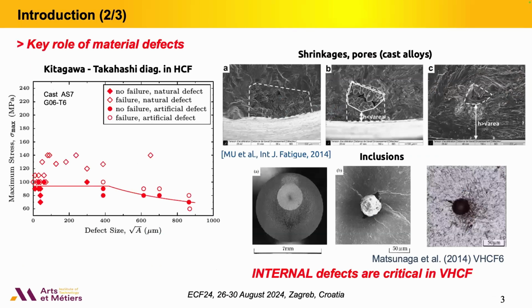So in very high cycle fatigue, the role of defects as a crack initiator, or trigger for the crack initiation, is very well known. In a high cycle fatigue regime, around 1 million or 10 million loading cycles, there is the very famous Kitagawa-Takahashi diagram. On the left, you can see the Kitagawa-Takahashi diagram, which gives you the effect on the fatigue strength at, for instance, 10 to the 7 cycles of the square root area of the defects. Up to a critical size, there is no significant effect on the fatigue resistance. And when the defect is too large, it decreases the fatigue resistance drastically.